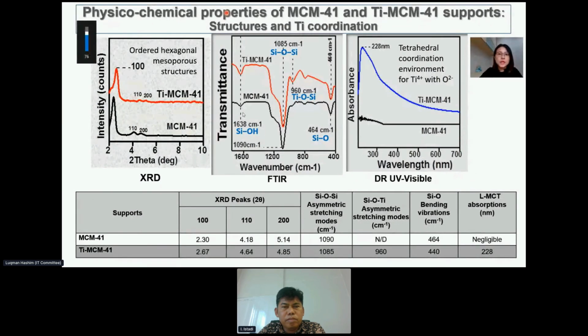Okay, so based on the chemical characteristics, which is the XRD characterization, which indicate the formation of the hexagonal mesopore structures for the MCM41, okay, while we can see there is a slight distortion of the hexagonal structures for this modified MCM41, which is due to the larger bond length of the titanium-oxygen-silica as compared to the silica-oxygen-silica linkage here.